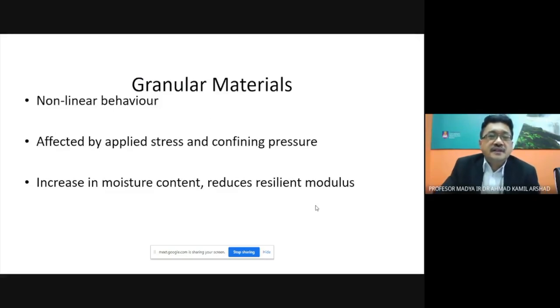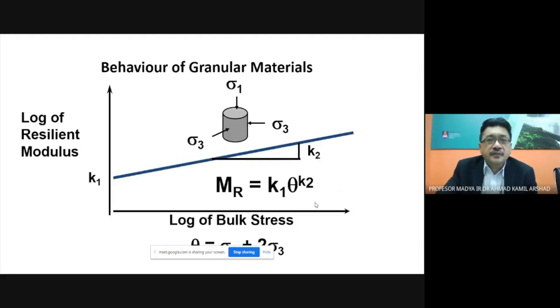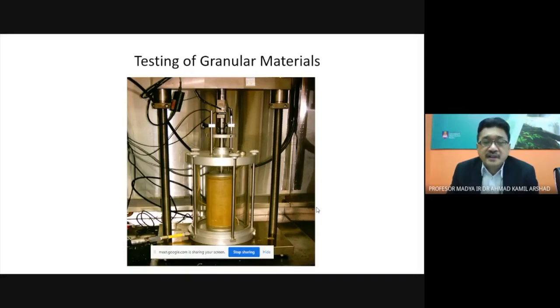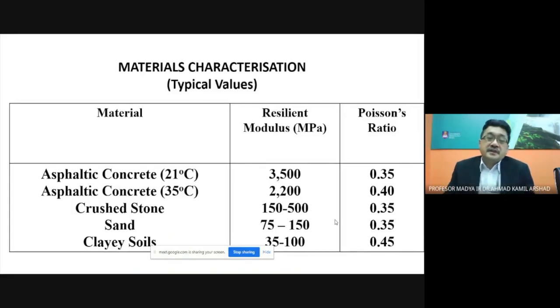For granular materials, they demonstrate a non-linear behavior, so it is affected by applied stress and confining pressure. Again, when there is an increase in moisture content, it reduces the resilient modulus. So this is a typical behavior of a granular material, which is normally for crusher run and sand. We use the equation MR equals K1 theta to the power K2, which is also known as the K-theta equation. So this will determine the resilient modulus of the granular materials. Normally, it is tested in a triaxial test with repetitive loading for granular materials and also the sand and subgrade. So these are some of the typical values used.